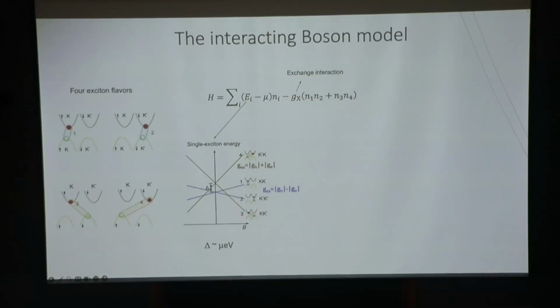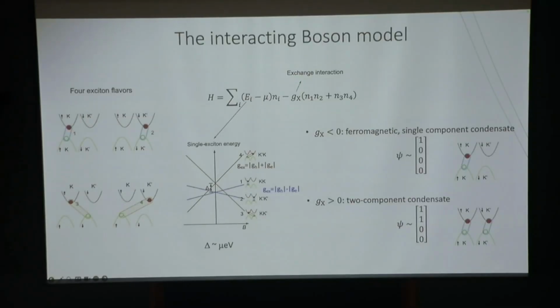When you apply a magnetic field, of course, there are Zeeman splittings. Intravalley excitons have a smaller Zeeman splitting because the hole and electron contributions cancel each other, so you have only their difference. The intervalley excitons have a larger Zeeman splitting because the g factors of electron and hole add up together. Now let's look at what the interaction does. If the exchange interaction Gx is smaller than 0, it will favor a ferromagnetic state, so you have a single-component condensate. On the other hand, if Gx is larger than 0, you want finite N1 and N2, which favors a two-component condensate. The situation is that Hartree-Fock calculation tells us that in our parameter range, Gx is smaller than 0.